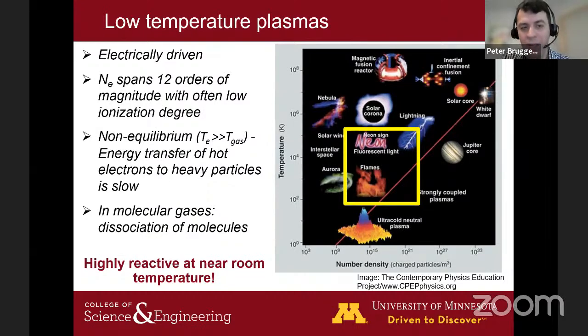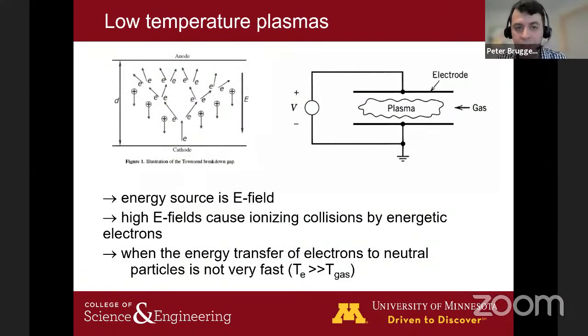And so why is this? Well, low-temperature plasmas are by definition, in most cases, generated by electric fields. Your electric fields accelerate electrons that are already present in the gas to high energies, and they cause ionizing collisions. So the energy you put into the plasma goes through the electrons. You're not directly heating the gas molecules with your energy source. And if you apply this in the correct way, you can actually avoid reaching equilibrium.